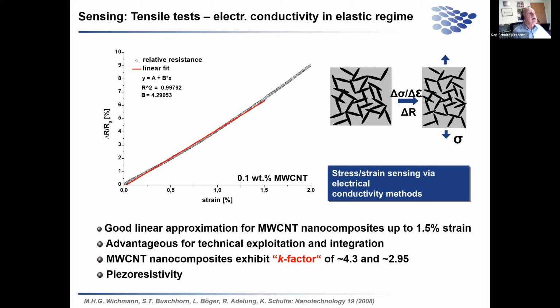Another thing one can use, and I'll go back for a moment from the fiber reinforced composites to the neat matrix system with the addition of carbon nanotubes: we have plotted here the increase in resistivity with strain. This is the test curve, and what you see here is this line, it's nearly a straight line. That means we have a very good and very high K factor over a quite wide range of strain.